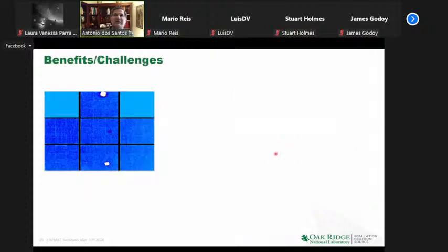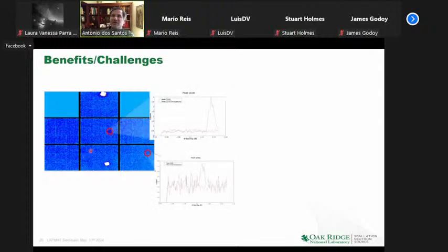One advantage is that now I have these single crystal spots here, and the powder signal is dispersed over the detector. This is another illustration of the higher sensitivity. You wouldn't know there was a single crystal peak there, but there is. You know this because if you know the unit cell, you can index and search not only in area but also in time of flight for where the peak would be, and indeed it is there.